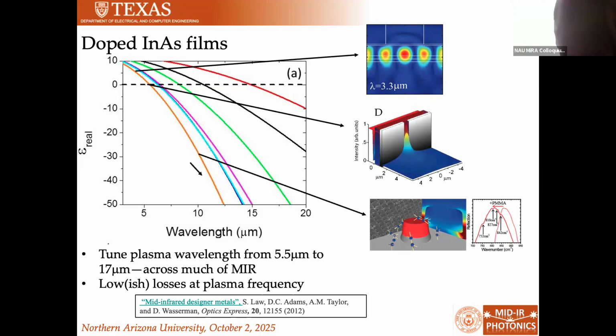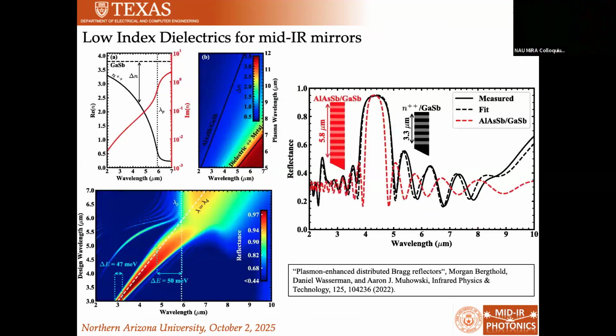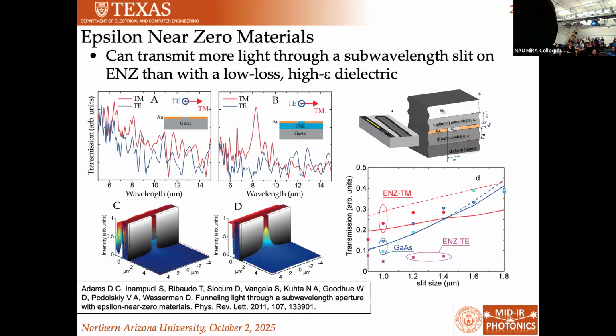And we have work in all of these different areas, right? So we can dope these materials in such a way that the refractive index is decreased, but it's not an optical metal. And then we can, for instance, make DBRs out of these, like reflecting mirrors. We can actually look at the region where the permittivity is zero. We showed that we can funnel light through really sub-wavelength apertures using epsilon near zero materials. This is an old work from when I was back at UMass.